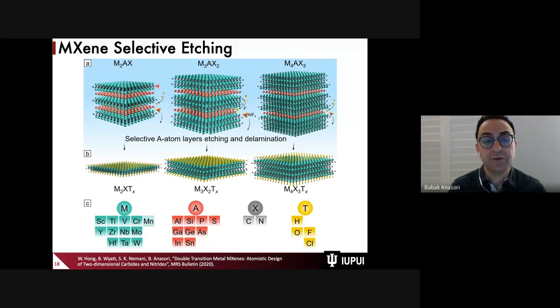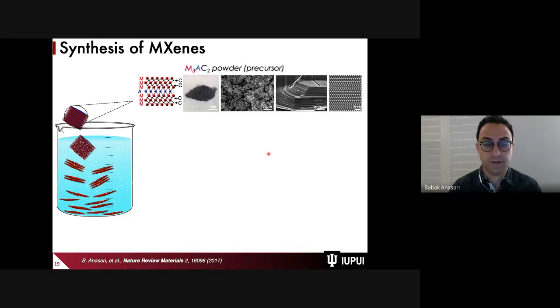After we make these, we remove the aluminum layers by selectively etching in hydrofluoric acid, and then we get the two-dimensional MXenes. Let me walk you through the structure using some microscopy. We have these bulk structures with the transition metal and these bonds. To the naked eye, the MAX phase, the precursor of MXene, is very similar to a carbide powder. It is grayish black, and this is just a photo of the powder. Under a microscope, it looks like any powder.